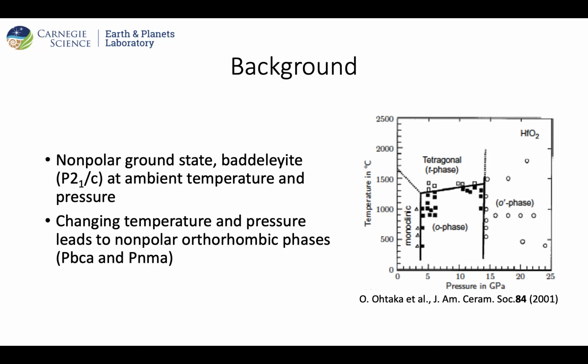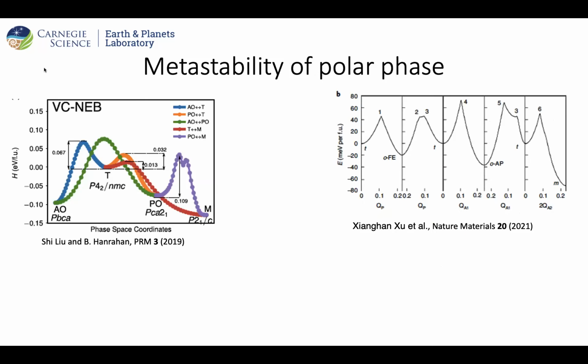Then came several studies which show that the ferroelectric phase, the relevant phase, the PCA2 sub 1, is metastable. Meaning, if we can actually drive the system from whatever state we have, let's say PBCA, through the barrier to the PCA2 sub 1, through electric field applications or strain, then we'd expect a ferroelectric phase to be stable.